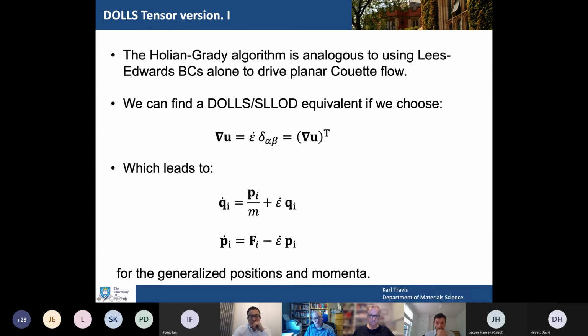The way this is done is to set the strain rate tensor equal to epsilon dot times the Kronecker delta tensor. I've deliberately put epsilon dot, not the same as eta dot on the last slide. I'll come back to that in a moment. It's not the same thing. Here are my basic Doll's tensor equations of motion with that strain rate tensor. That's for the q and the p.